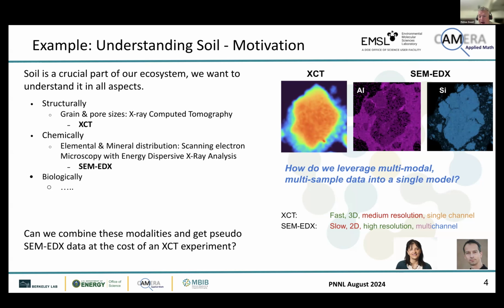XCT is fast. It's three-dimensional, medium resolution. It's just single channel though. SEM EDX is slow-ish. It's 2D. It's very high resolution, and it's multi-channel. So it would be extremely nice if we can take our three-dimensional XCT map and then somehow in-paint it with realistic SEM EDX data.